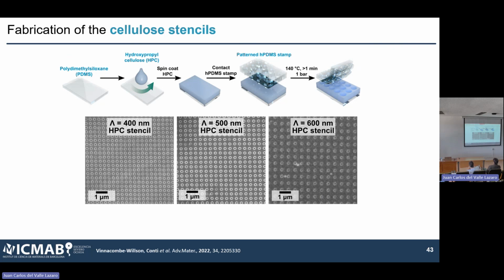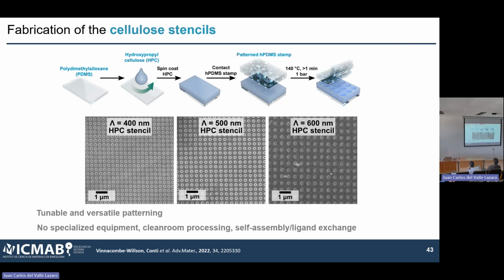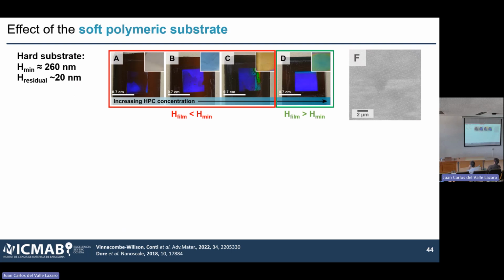Okay, so we show that we can create an HPC stencil or fishnet, whatever you want to call it, with different lattice parameters, and these are actually extremely thin. These are 30 to 40 nanometers thin. I don't know if there are some experts in nanoimprint lithography here, but normally when I say that we can get down to 30, 40 nanometers thick, they look at me with a very weird and ugly face because they're like, that's not possible, which is true.